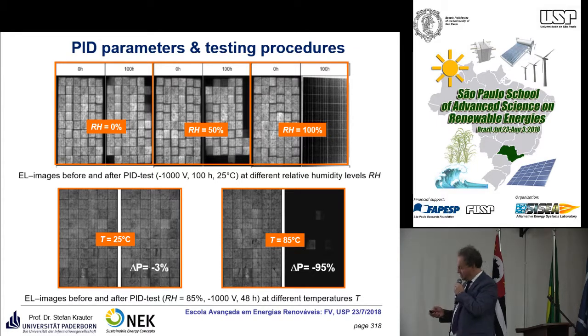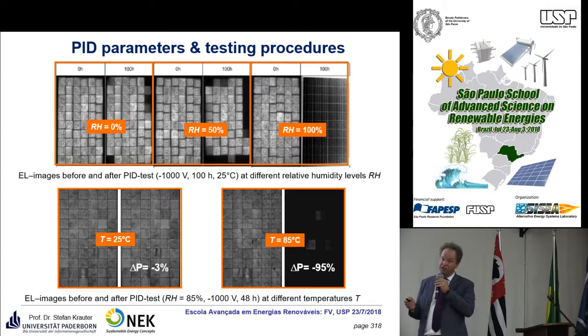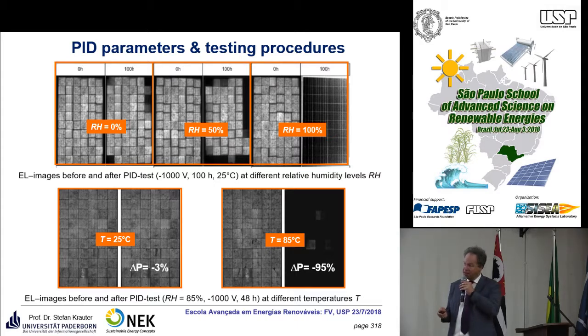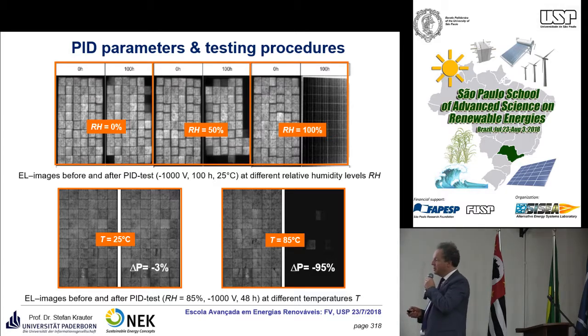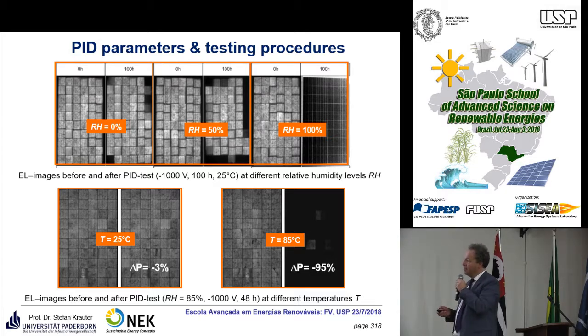Here you see, for example, at zero humidity, like in Sao Paulo now, that nothing happens. If you have a lot of humidity, like often in Rio, then you have a very strong PID effect. Then there's a high leakage current, and a lot of sodium ions block the PN interface in the modules. Also the temperature effect: at 25 degrees almost nothing happens, 3 percent power degradation. If you go to 85 degrees, 95% of the power. This is a very extreme case, so not often, but it occurs that you have a high power reduction.